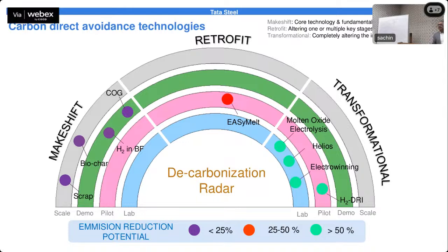Retrofit, there are not many technologies in the retrofit area. The easy melt is one where you do dry reforming of methane. And this methane can come from coke oven gas. You do dry reforming, and you get carbon monoxide. But it's a technology which is at a demonstration pilot scale, longer term, and has 25 to 50% efficacy in carbon reduction. All the higher reduction potential technologies are all transformational.